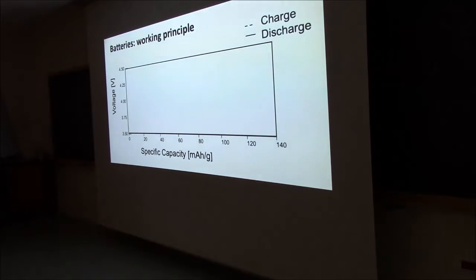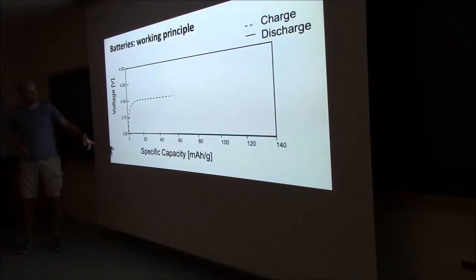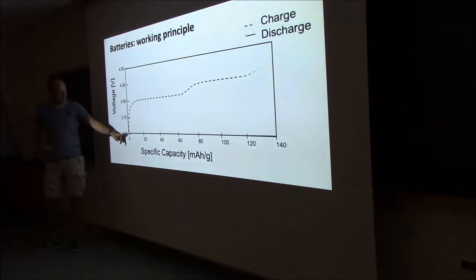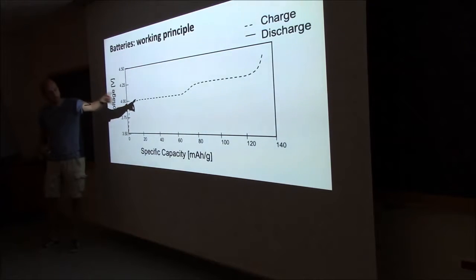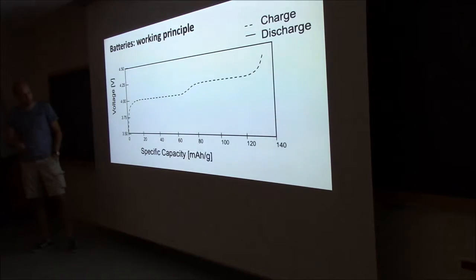We'll show you some pictures about how you can test them in our lab. The kind of measurements that we do, if you do charging and discharging, is where you will see that during a charging, you provide a current, you will see that the voltage will go up. And then within a specific capacity range, it will do this, and then it will reach a number of something like 4.5. You can see that around 4, there are 2 plateaus, and this holds for lithium manganese oxide,